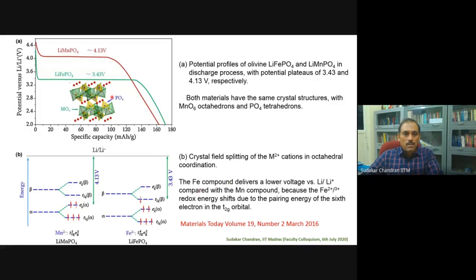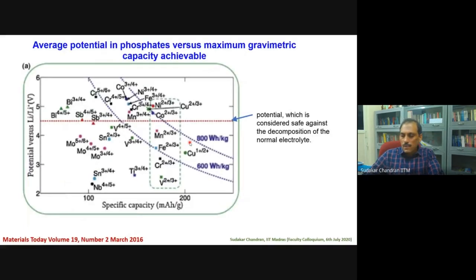But then they found that this exhibits lower voltage, and it is in fact the redox energy levels that get shifted due to the pairing energy. So the sixth electron, which gets occupied here, controls the energy level as well. What controls the voltage in these compounds was thoroughly investigated by Goodenough's group. And of course, many different polyanionic compounds were investigated since then.